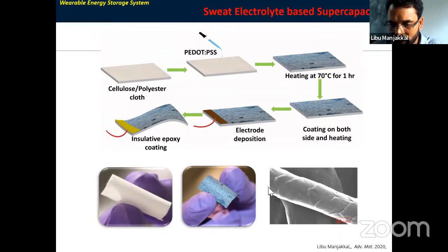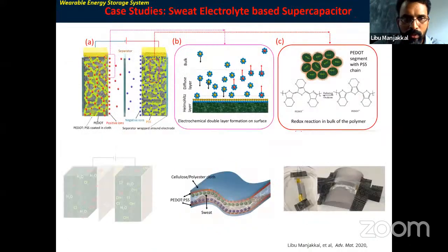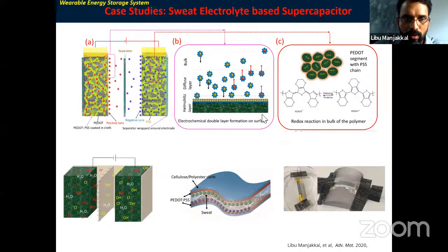You can see here that the cloth is converted into a PEDOT:PSS conductive cloth. Then I checked each fiber, how the PEDOT:PSS is distributed, and it is uniformly distributed on the surface of the electrode. Then I applied a potential on these two cloths separated by another cloth, which acts as a separator. I covered the electrodes with this separator, and when the separator is wetted by sweat and I applied a potential, you can see that the positive and negative ions form an electrochemical double layer. In previous talks, I already explained the electrochemical double layer and the pseudocapacitance reactions. PEDOT:PSS is a highly conductive material, and EDLC is formed on the surface of the electrode.